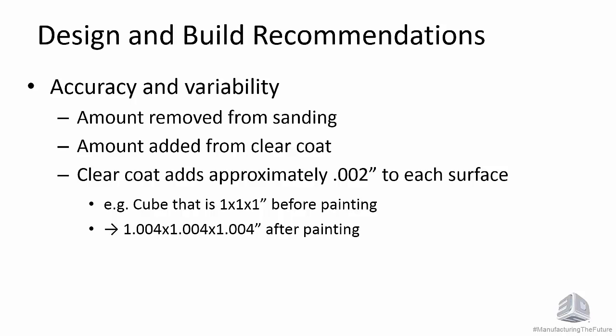And then there's the amount added by clear coat. Typically, it adds about 0.002 inches to each surface. That's just a good estimation number. So, for instance, if you take a 1-inch cube, after spraying with clear coat, it becomes a 1 inch and 4 thousandths cube because it adds 2 thousandths to each surface. And since there are two surfaces where you're going to be measuring, it increases it by 4 thousandths.